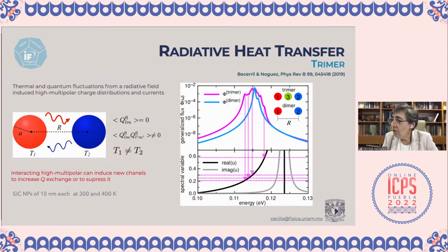What is interesting is, for example, that we can identify where we can increase this radiative heat transfer, but we can also control or modify this heat transfer by looking at a third nanoparticle, and we can increase the energy window just by immersing a third one in between these two nanoparticles. So we can control the heat transfer, the energy transfer, in some way, by having different arrays of nanoparticles. If we have two, or if we have three, we can increase the energy windows and the amount of generalized flow of the heat transfer in the system.